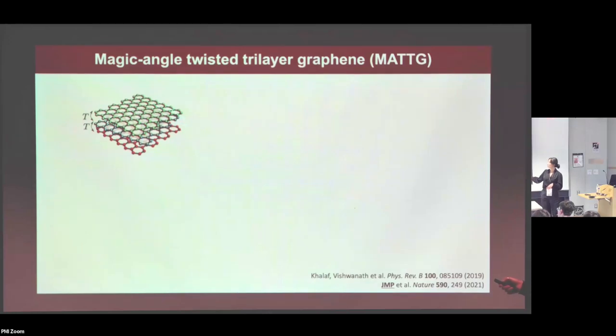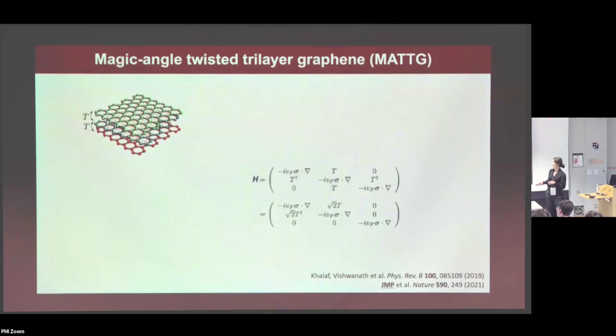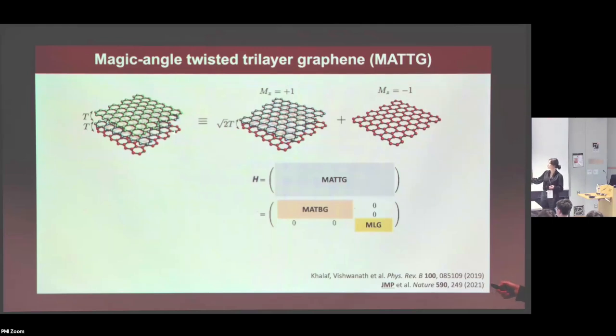But with this symmetrical twist, by theta and minus theta, we end up with only a single Moiré periodicity. In this case we can simplify the original Hamiltonian into a block diagonalized form, with a block that is like magic angle twisted bilayer graphene and a separate, coexisting monolayer graphene-like block. So we can decompose twisted trilayer graphene into a twisted bilayer graphene-like structure, but with a square root of 2 larger interlayer tunneling factor that came from the block diagonalization, plus a monolayer graphene. Because of this factor, the magic angle for making this block flat requires the twist angle to be exactly square root of 2 larger than the magic angle of twisted bilayer graphene. So 1.1 times square root of 2 gives 1.56 degrees.